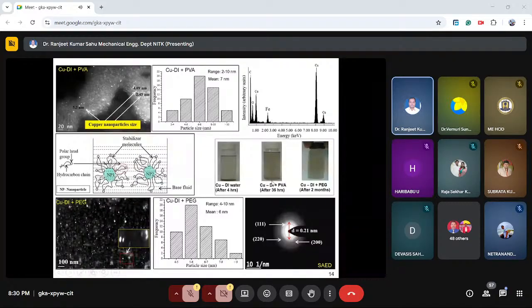To overcome this problem, we carried out various experiments to identify the stabilizer as well as the surface chemistry. Finally, we adopted polyethylene glycol as one more stabilizer. By using this stabilizer, the size of the particles lies in the range of 4 to 10 nanometer with a mean size of 6 nanometer, and excellent dispersion stability of the copper particles dispersed in the solution has been found. After 2 months there is no settling of particles, and after 6 months also no settling takes place. Excellent dispersion stability has been obtained.